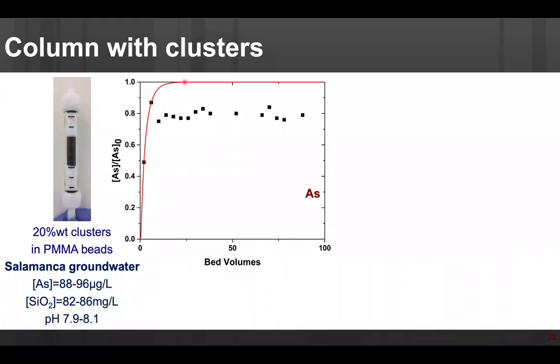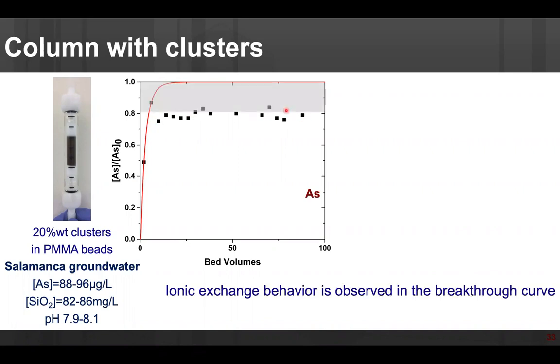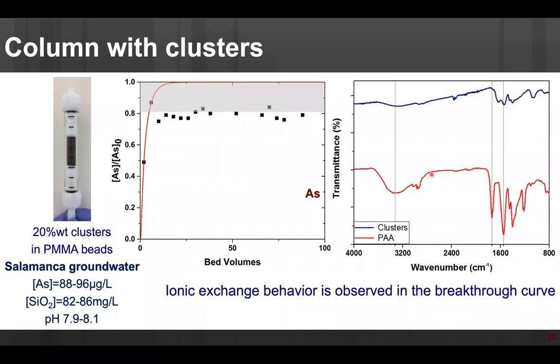But still, the performance in columns was bad. I found that even when the concentration increased very fast, it never fully saturated. Looking at the literature, this looks like an ionic exchange behavior. I wanted to look at the IR and see, okay, I'm using a polymer as a precursor. Of course, I still have it on the surface. So when I'm flowing arsenic, some arsenic is being absorbed, that is what is getting in here, and we are releasing that polymer. That's the reason we have this behavior.